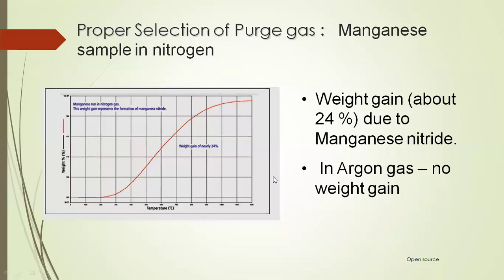Now, selection of a proper purge gas. See, I told you that we can do the TGA in air or in nitrogen. But what if my sample itself is reacting with either air or nitrogen? Here is an example of manganese. The sample is run in nitrogen, and manganese forms manganese nitride when you're heating in nitrogen. So you get a weight gain in this TGA rather than weight loss. So one starts puzzling, why am I getting weight gain? Because your sample is reacting with the purge gas. Simple, change the purge gas.